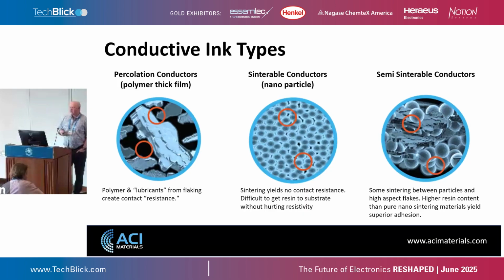In the conductive ink space, you have three different conductors. You have the traditional polymer thick film, which are percolation, where particles touch and you get the electrons jumping from particle to particle. But there is some resistance as you have resin in there for your adhesion to your substrate. You've then got nanomaterials, very tiny materials below 1 micron. They pack well, give you very good electrical performance, but you can't put enough resin, adhesion promotion materials in there to get great adhesion. So we work with semi-sinterable conductors. That's mixtures of particle sizes that actually sinter at low temperature to get very high conductivity.